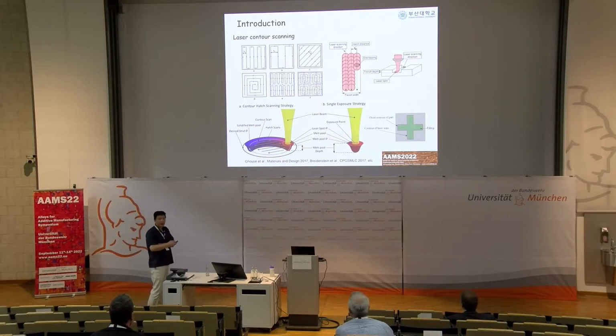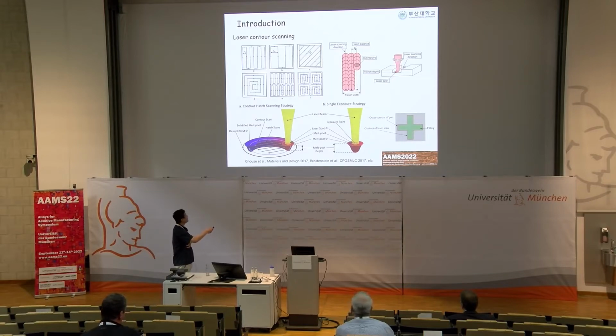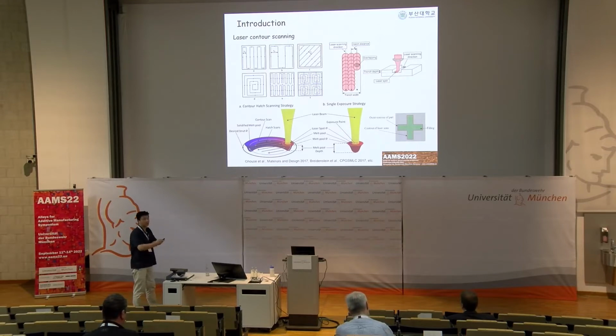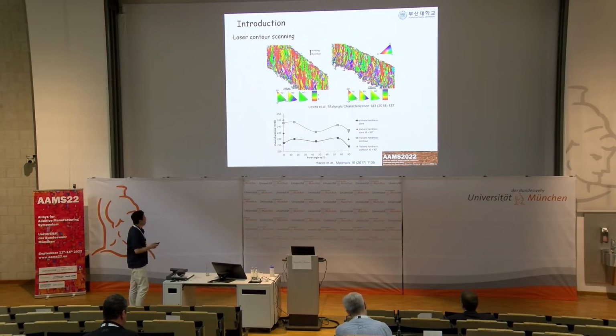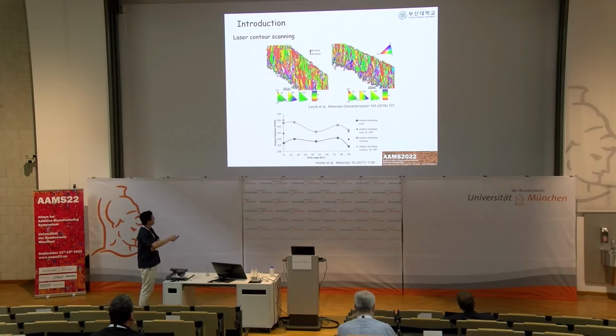If our component size is big enough, then the effect is maybe negligible. But if we have a lattice structure or an internal structure with small size, then the area that is influenced by the laser contour scanning would influence the overall performance. There are several studies showing completely different microstructure near the outer surface of LPBF parts, for whatever reason, maybe from the contour scanning and maybe from the unmolten powder and so on. There are also studies showing slightly different local mechanical properties as well. For instance, local micro hardness can vary from the core to the outer surface. Usually it's higher.